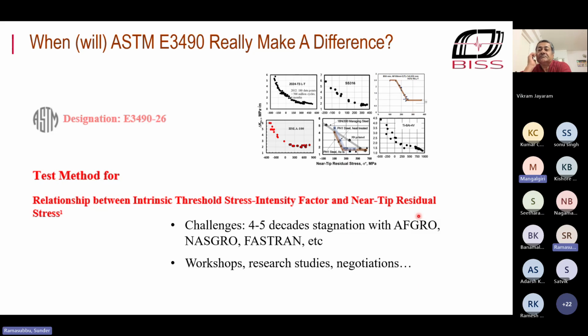Well, if you look at most materials, they do have a plateau. They kind of flatten out towards the right. One exception is titanium, because in titanium, as you keep pushing the near-tip residual stress to the right, you start getting the time-dependent effect, because titanium creeps at room temperature. So that's what comes in the way for titanium.